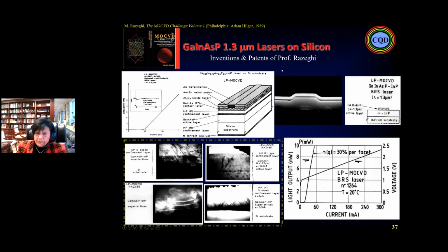And at the time, I put that on a silicon substrate, and I demonstrated that with a few monolayers at the interface between indium phosphide and the silicon substrate, we can have excellent results. That is the excellent result that you can see with continuous wave. It was measured at CNET in France, who are the experts in telecom, and they said this laser is good because it's on silicon. And you know that now, after approximately 35, 40 years, the dream of everybody is to put everything on silicon, and especially the laser.